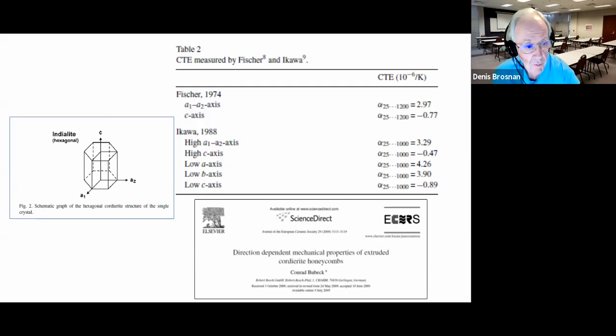Now, cordierite's a kind of interesting mineral, and here's a little diagram of a hexagonal crystal of cordierite. It shows a C crystalline direction and two A crystalline directions. In 1974, it became known that in a couple of the A directions, the thermal expansion coefficient was 2.97, but in the other direction, it was minus 0.77. There was some other work that made that a little more definitive later on. Here's a reference that you can look at if you're really interested in it.